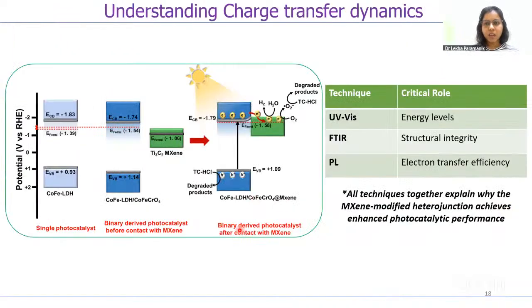Finally, after concluding all the results, I was able to give a possible reaction mechanism, which is helpful in understanding the charge transfer dynamics in my material. The cobalt iron LDH has an optical band gap of 2.75, and in combination with the valence band analysis, valence band and conduction band, I was able to determine minus 1.83 volt.